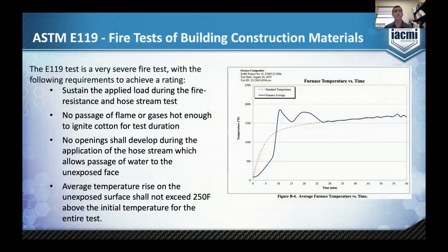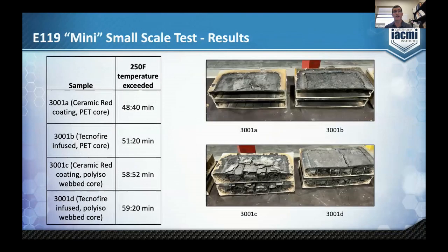So here's the E119 test. So I should back up here for a second. After these mini tests, it was determined that the polyiso was a better core, and the Technofire coating was a better coating. The webs actually provided pretty good protection for the panel, because the surface that was exposed to the furnace or the temperature pretty much got destroyed in all cases, but the webs and the backside were still intact and provided good structural strength.